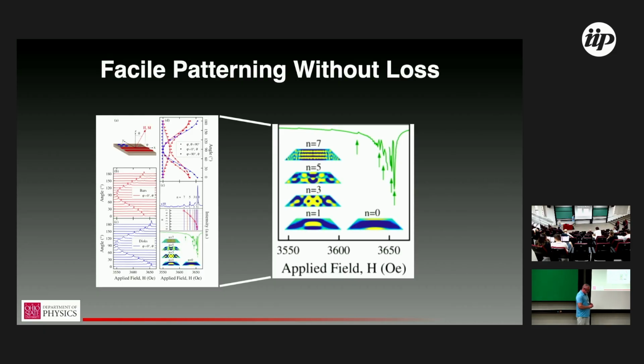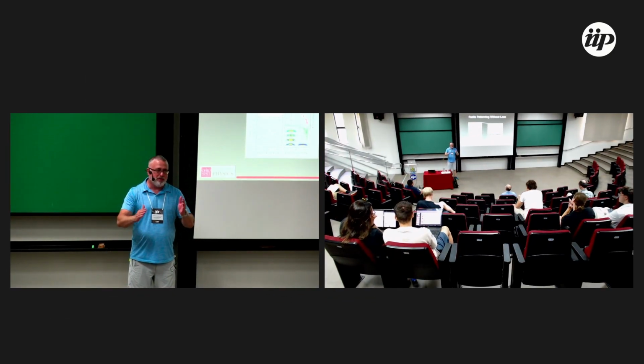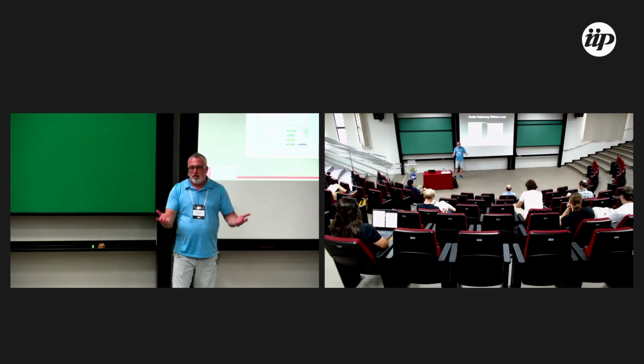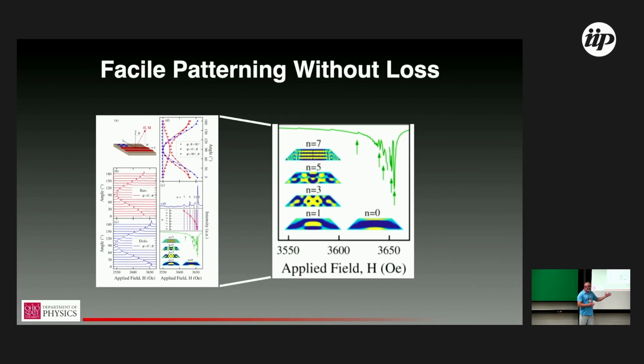Yeah, so it's basically the materials effect that no surface is really equivalent to the bulk. In a perfect crystal, this is the background I came to from a solid state perspective, if I have an infinite perfect crystal and I cut it, then the atoms at that surface are not fully compensated. They have some dangling bonds that aren't being matched by the atoms that are missing from the other side of the interface. So that typically causes a reorganization of that surface where you get some distortion of the lattice. And that distortion can change band gap, magnetic properties, et cetera. There's also potentially some chemistry at the surface. I mean, we try to keep it air-free, but maybe there's a thin oxide forming. That typically happens with thin film magnets.